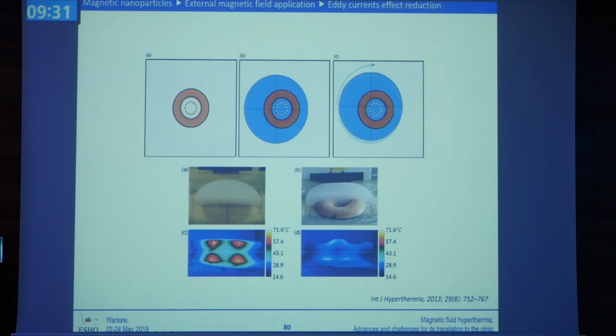So they thought, let's move the coil. If you have a rotation or a translation of the coil, you smooth out these high values of heating. You keep the nanoparticles inside the magnetic field, but the eddy currents get dispersed inside your healthy tissue and they don't heat up the healthy tissue. So this is one way of getting around the Brezovich criterion, and it's something that perhaps people can use in the clinics to apply the magnetic field to patients that are administered with nanoparticles.